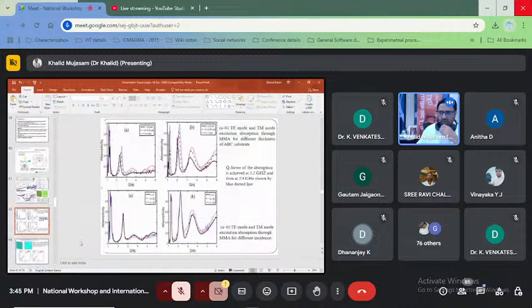So moving on, as I said, we were looking at how we can use this. So we had two modes here. In the transverse mode, what we saw was that Q factor absorption was achieved at 1.2 gigahertz, and then again at 2.4 gigahertz, shown by the blue dots. So the absorbance was very high.